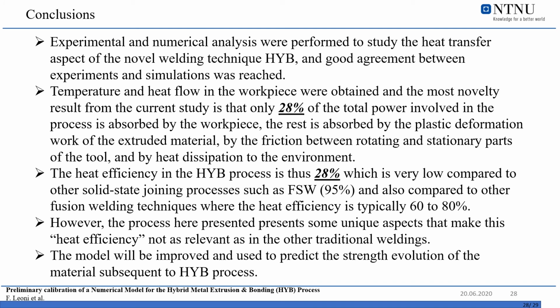So, in conclusion, with this study, a good agreement between experiments and simulations was reached, and what was found is that only about 30% of the total power involved in the process is absorbed by the workpiece. The rest is absorbed by the plastic deformation work of the extruded material, by friction between rotating and stationary parts of the tool, and by heat dissipation to the environment. The heat efficiency of this process is thus very low compared to other solid-state joining processes such as friction stir welding, and also compared to other fusion welding techniques where the heat efficiency is typically 60–80%.